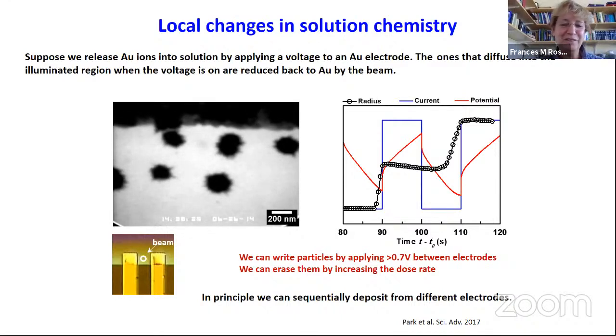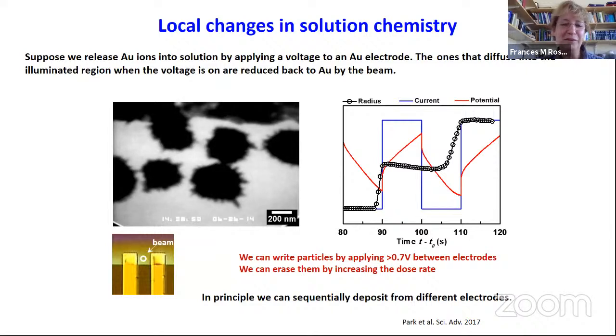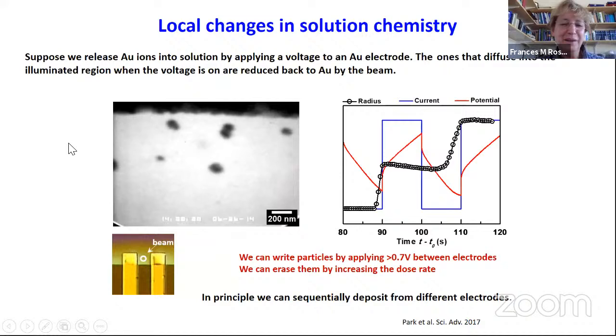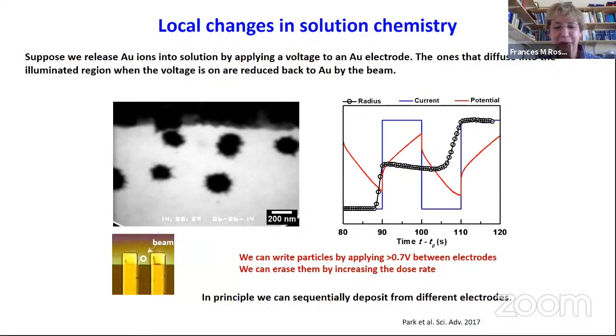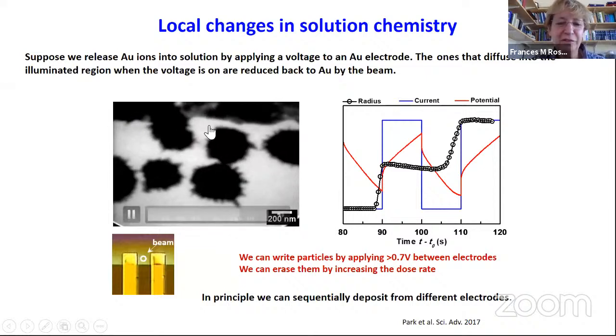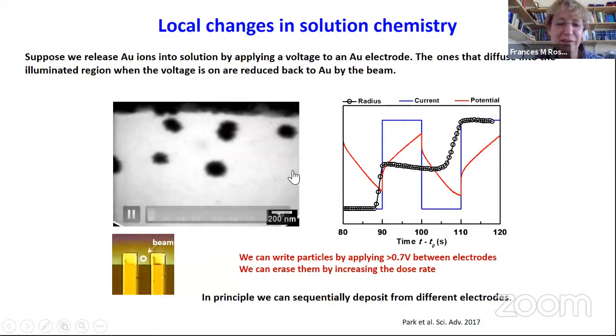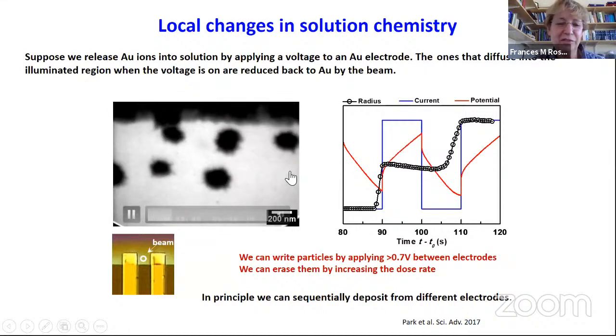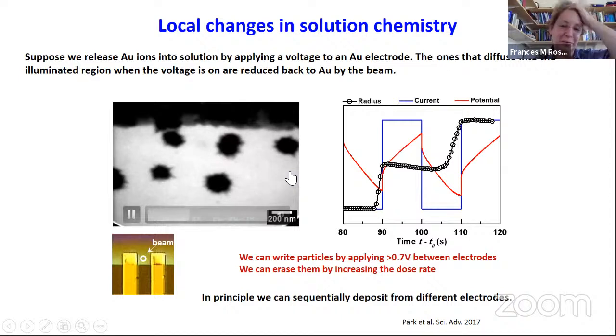This is the reduction of metal ions into particles. And what we're doing is we are applying a voltage to an electrode, which is up the top here. We are using the voltage to release gold ions into solution. And then the ions diffuse away, they've diffused to here. And now the electron beam is illuminating the electrolytes, and the hydrated electrons are reducing them into gold particles.